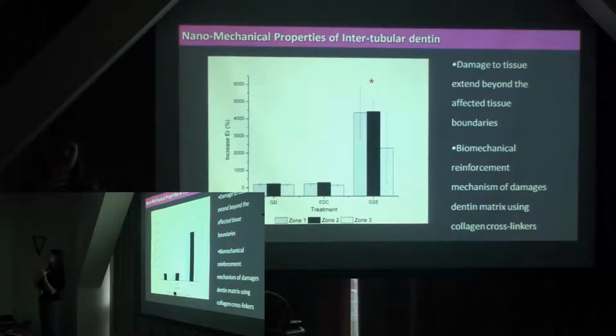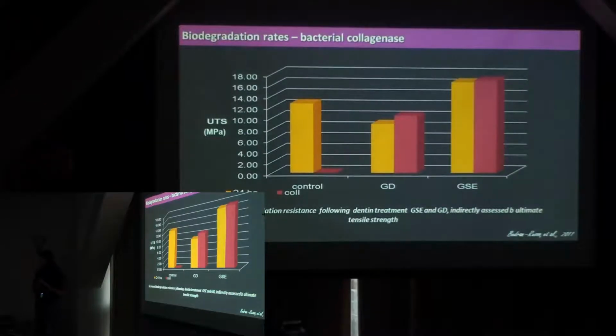And the reason for that is that collagen, where the decay process was taking place, was already being partially degraded and lost some of those crosslinks. So there was an ability for it to promote even more cross-linkage.